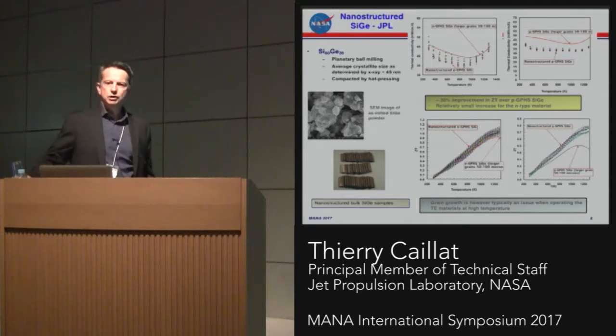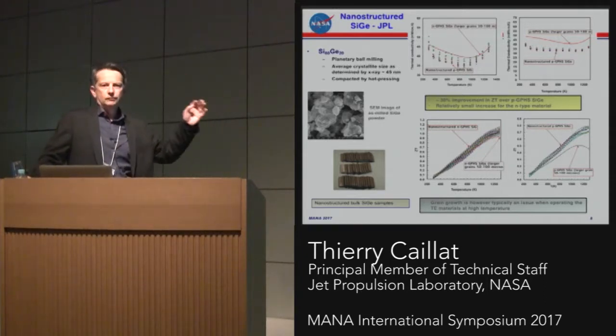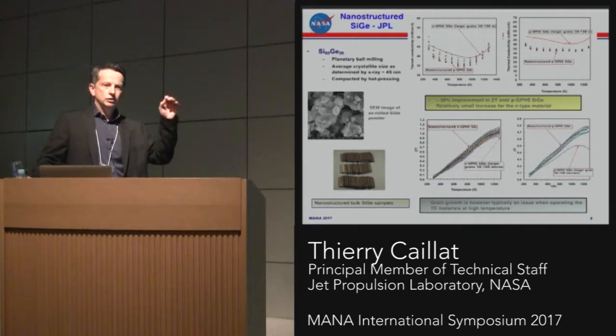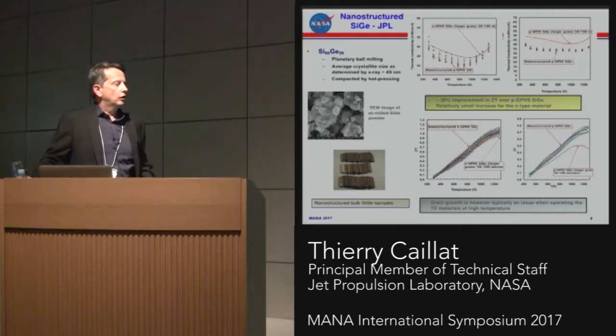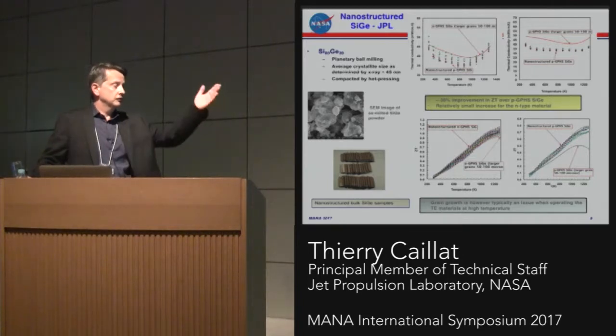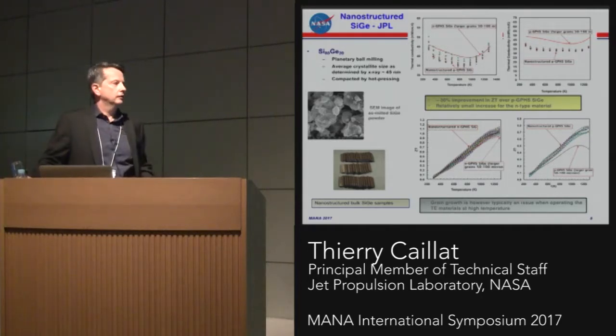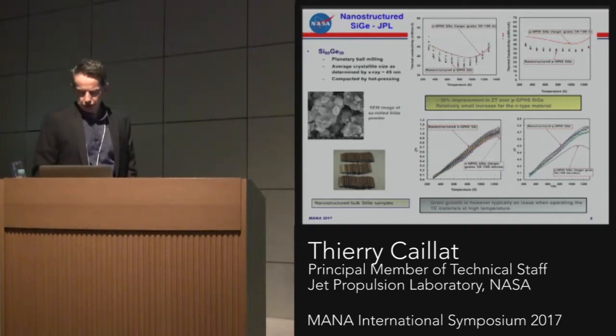Specifically for our application, we're going to be running those devices for 20, 40 years. And as I mentioned, we are running at pretty high temperatures. So grain growth is potentially an issue. These gains that have been reported in the literature are true and real. But the problem is, when you operate at 1,000 degrees C, you're going to get grain growth, and then you revert back to a micron-sized grain, which reverses your ZT to the original value. So for us, it has been difficult to apply the nanostructured materials, even though, for a short period of time, you can see some gains. This is a challenge for long time operation.